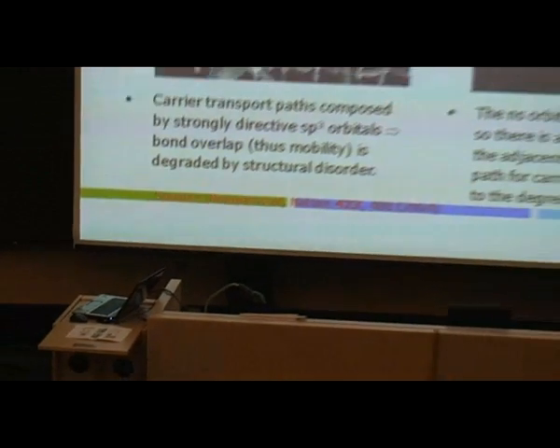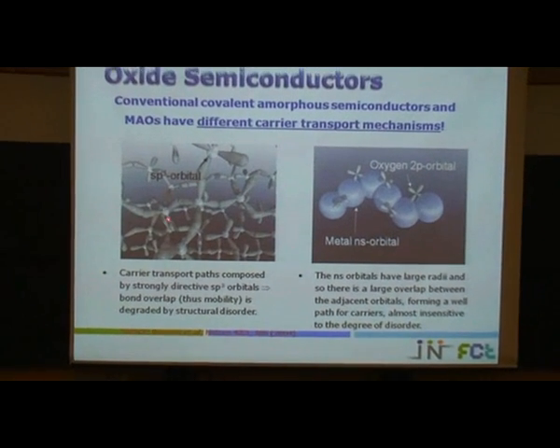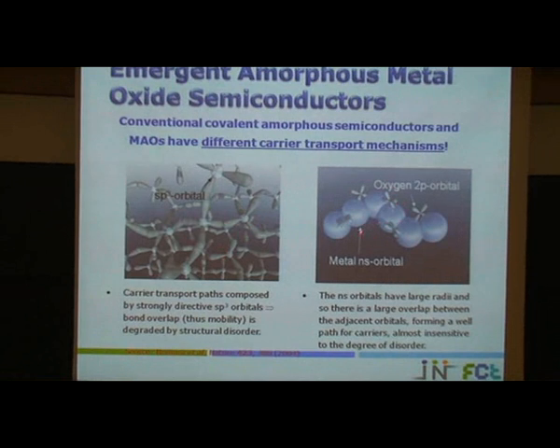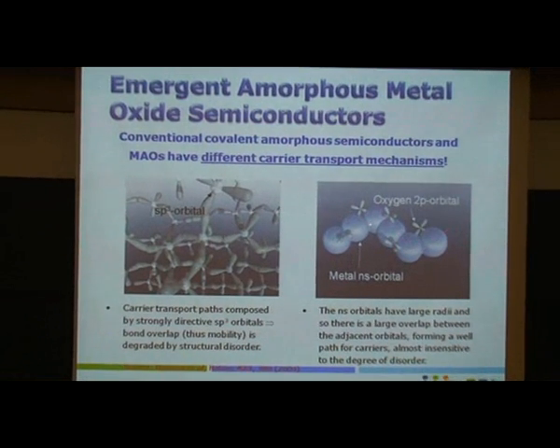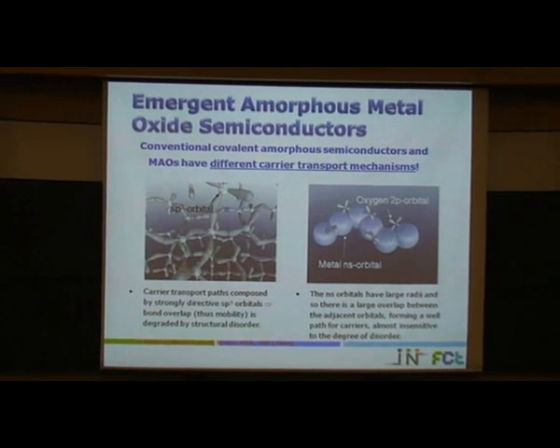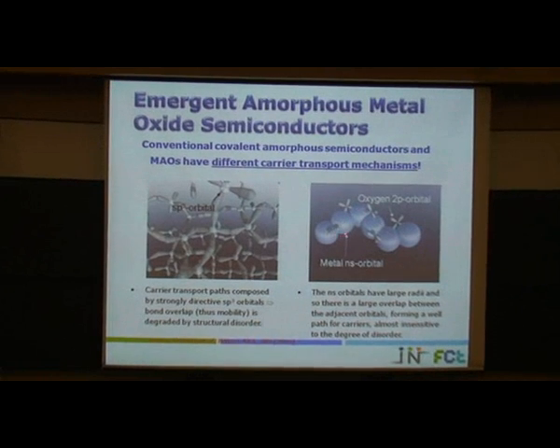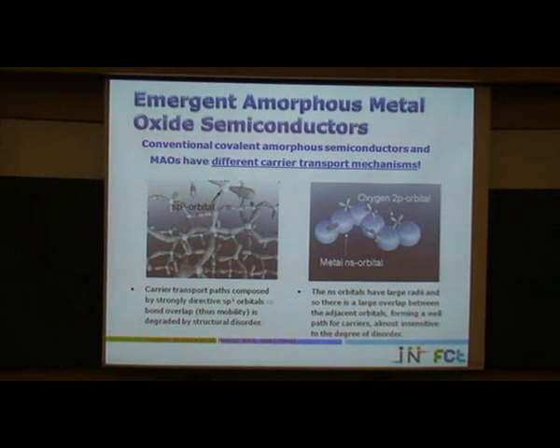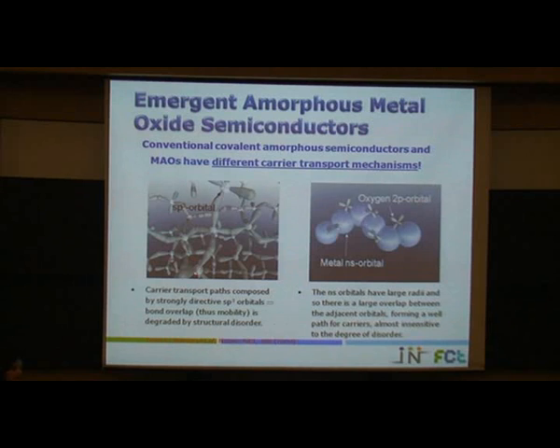And for example, here we have a comparison between amorphous silicon and these amorphous oxide semiconductors. These are the metal s orbitals. Both materials present a disordered structure, but here we have some overlapping of the orbitals, and we have a conduction path for the electron. So in this case, the disorder does not limit the electrical properties, for example the mobility of the material, because the conduction mechanism is different from the conventional covalent semiconductors. And that's why we have such a high value of mobility for an amorphous semiconductor.